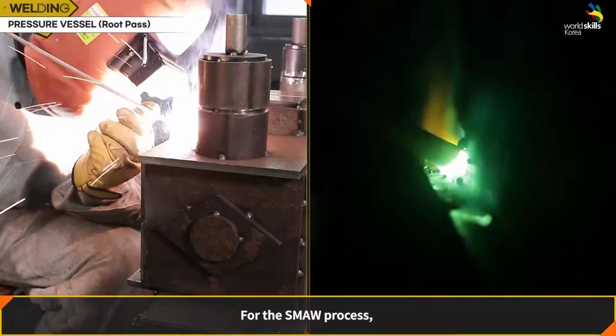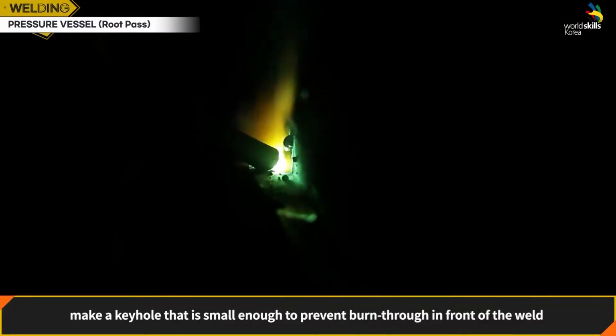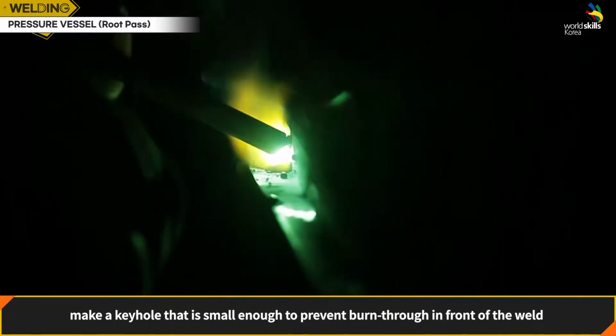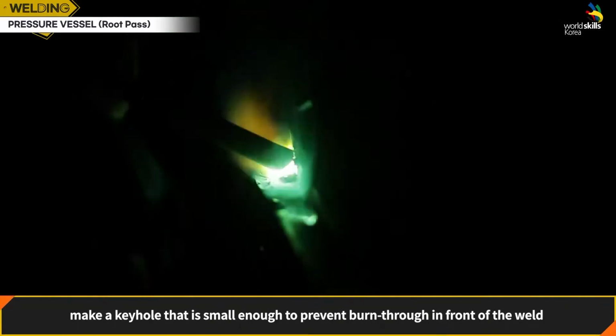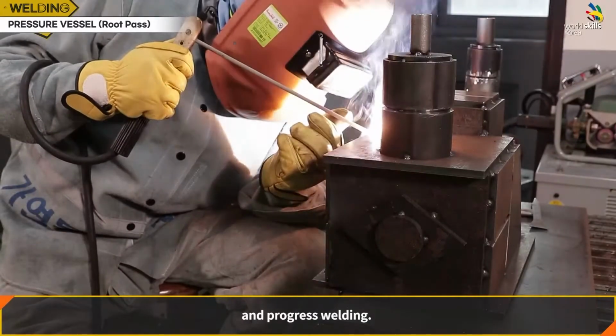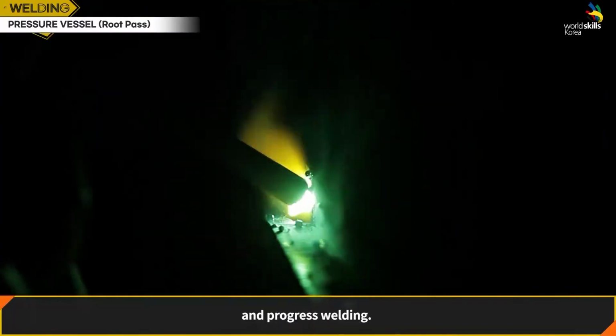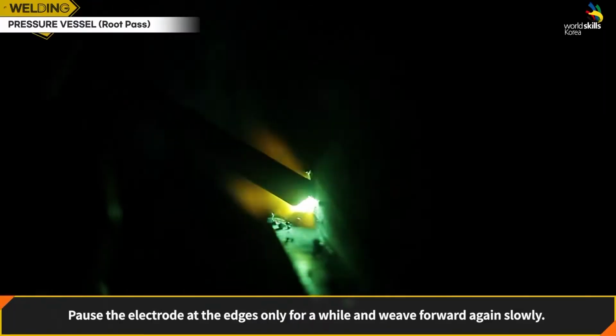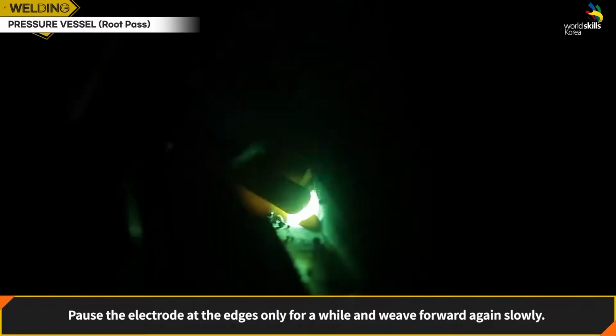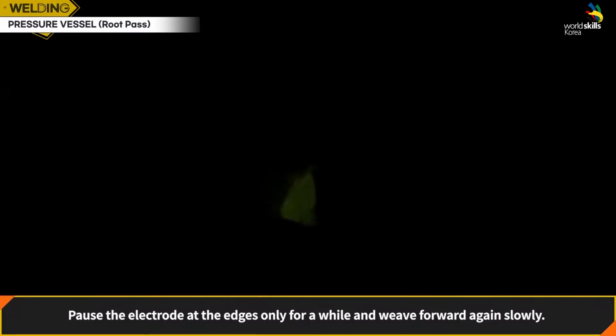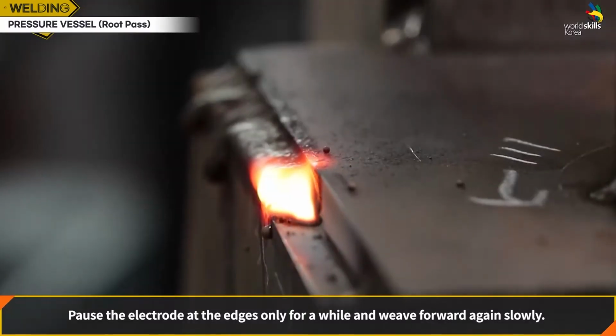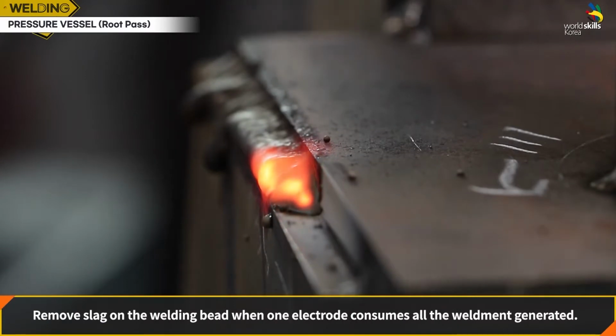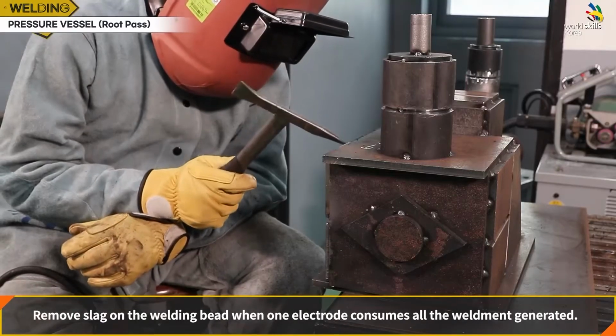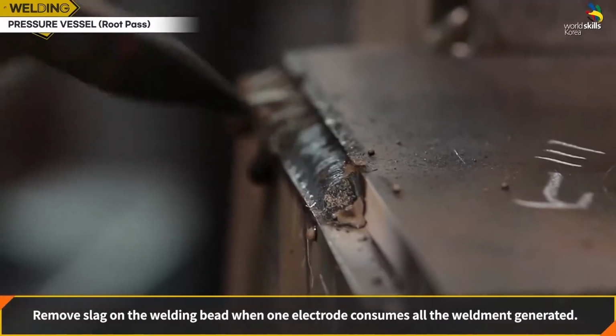For the SMAW process, make a keyhole that is small enough to prevent burn-through in front of the weld, and progress welding. Weaving the welding rod slowly while staying on both sides of the corner, little by little. Remove slag on the welding bead when one electrode consumes all the weldment generated.